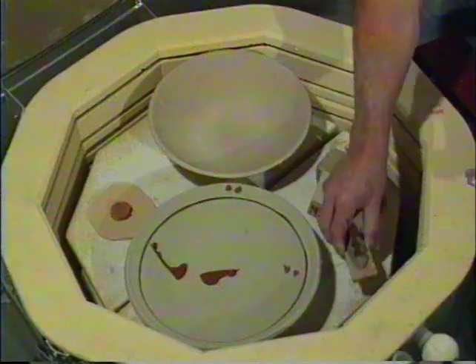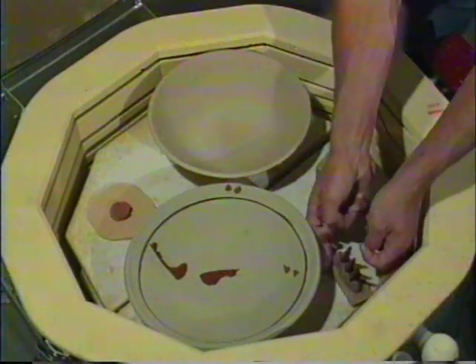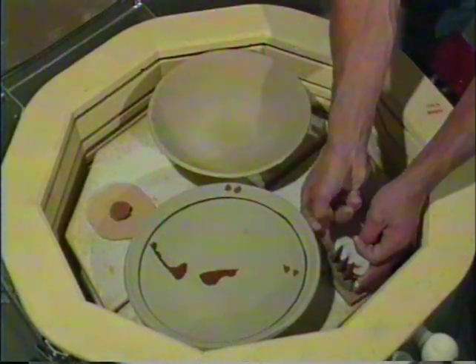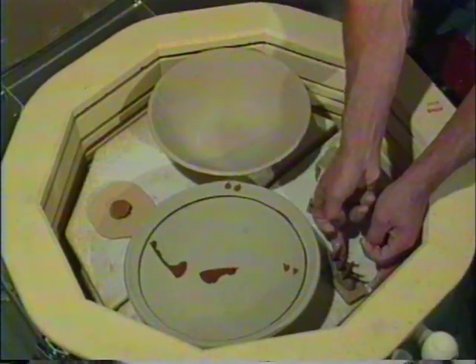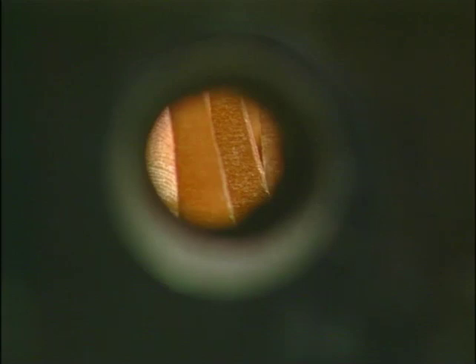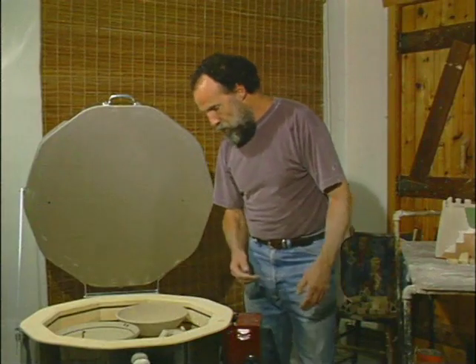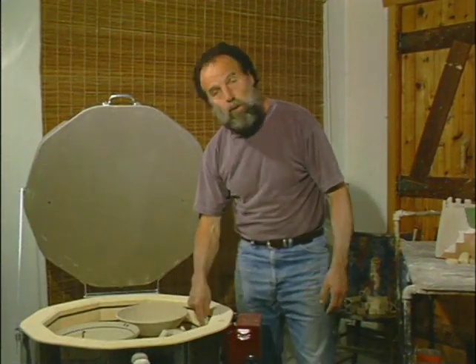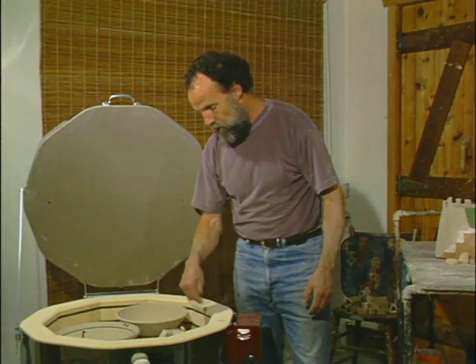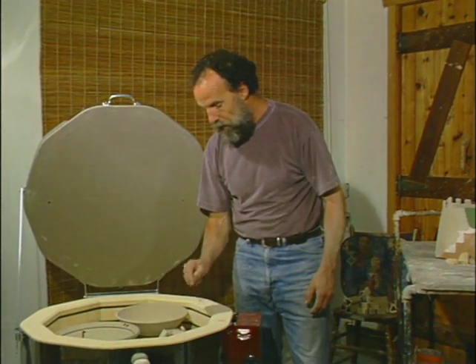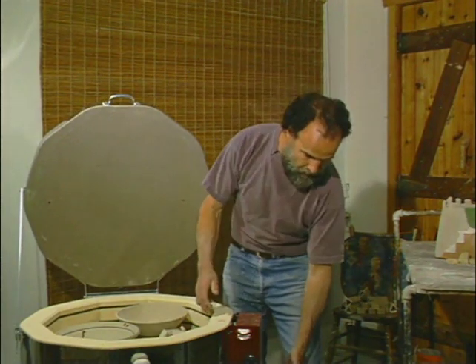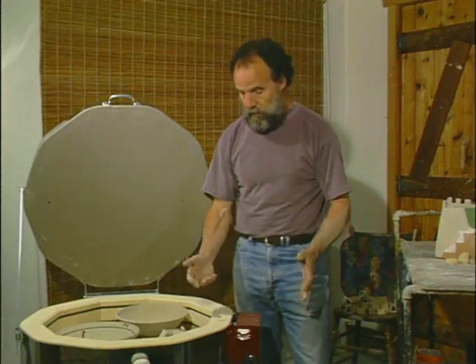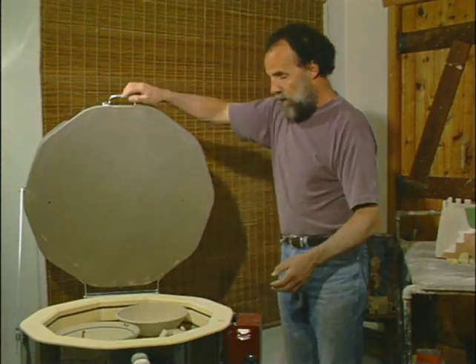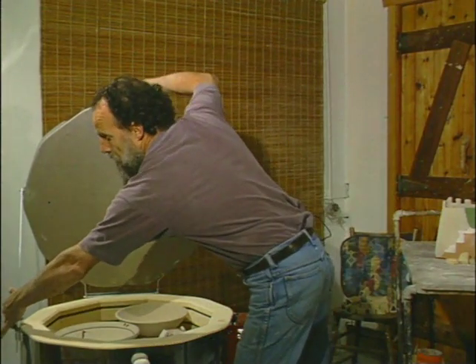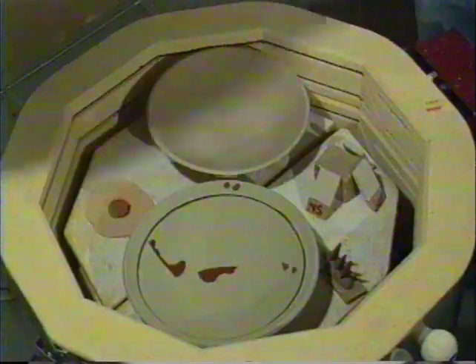Now we'll place that in, as we did with the bisque firing, so that the cones will fall across our field of view. So place them at a slight angle to the center line of the spy hole. Last thing we'll do is check that the guard cone is in the kiln sitter, that its little cone is placed correctly, and I can see down there that it is, and that the sitter's armed on the outside, so everything's set for our kiln sitter. And the last thing we'll do is close the lid, and we're ready to fire.